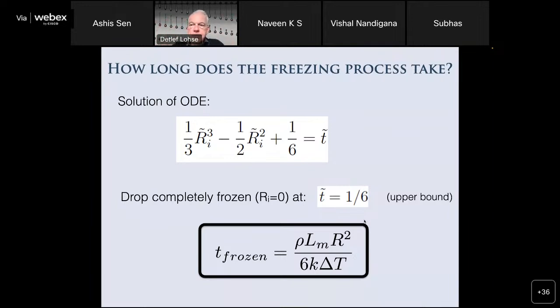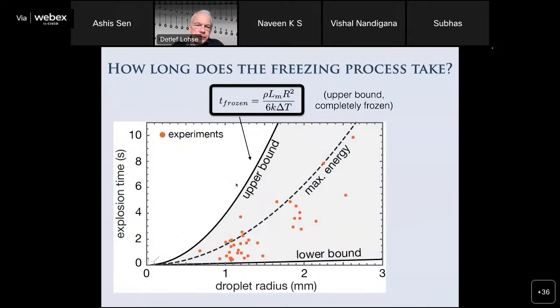And that's, of course, the freezing time for the front going from the outside to the very center. But sometimes the pressure is already higher earlier, when part of this water is not yet frozen. So this is, so to say, an upper bound. And this is this curve here. So here I show you the explosion time. And this time that it freezes from the outside to the inside is this upper bound going like r squared. Those are the data. So indeed, they are all under this upper bound. So this is the data explosion time of the droplet versus the droplet radius.